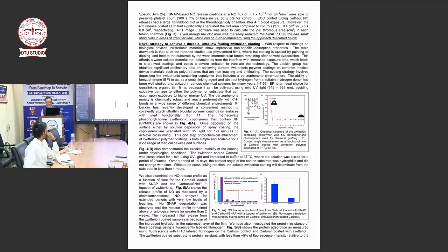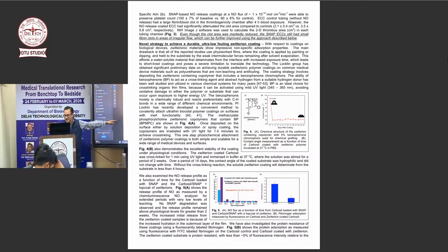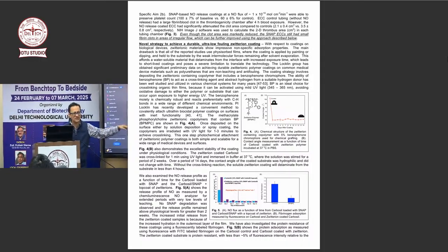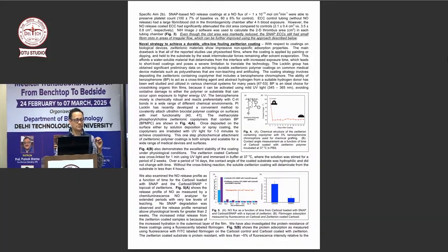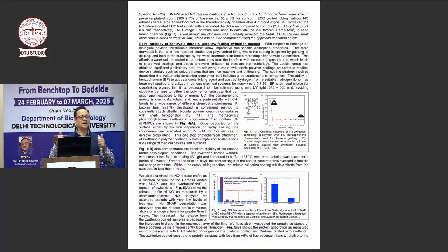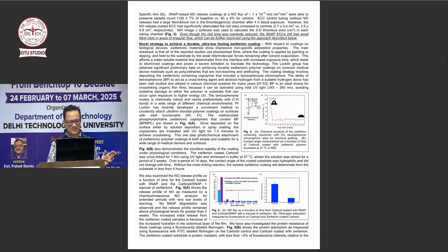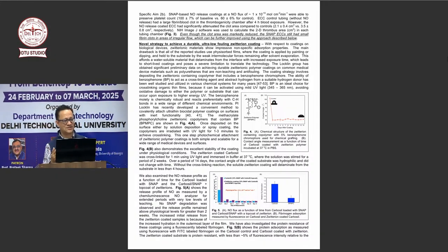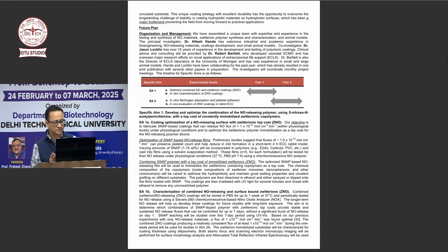And then we say, but when we did the fibrinogen study, my nitric oxide with zwitterion surface, the left one, had significantly less fibrinogen adsorbed. So the zwitterion is also doing its work. Nitric oxide is also getting released. That's it. That's our preliminary data. Now we are moving to the future plan.